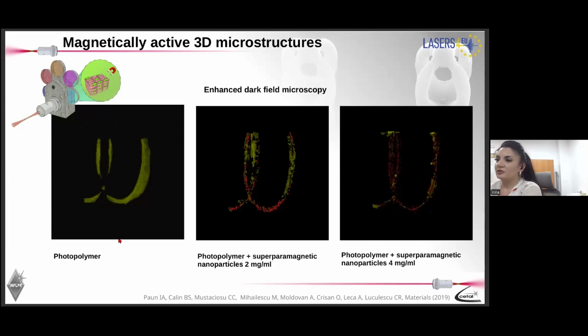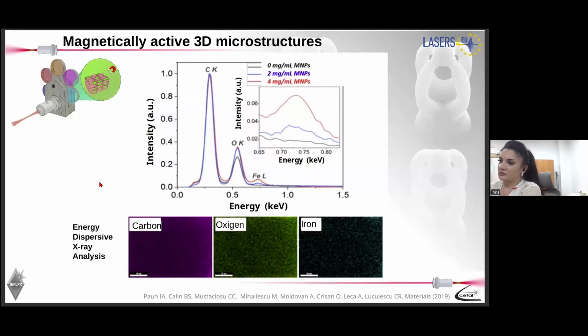Again, as in 2 dimensions, in 3 dimensions we wanted to see if we have magnetic nanoparticles, or at least, okay, now we don't know yet that they are magnetic, but at least to see that we have some nanoparticles inside the volume of the structure. We used enhanced dark field microscopy images, and you can see here in red dots, of course false colors, the nanoparticles within the polymer, which is marked with green. We checked again, also in this 3-dimensional case, that we have magnetic nanoparticles. You have here EDAX measurements.